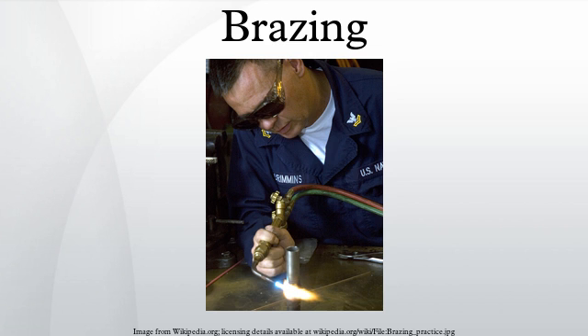Combusted fuel gas: 87% N2, 11 to 12% CO2, 0.5 to 1% CO, 0.5 to 1% H2. For silver, copper phosphorus and copper zinc filler metals. For brazing copper and brass.